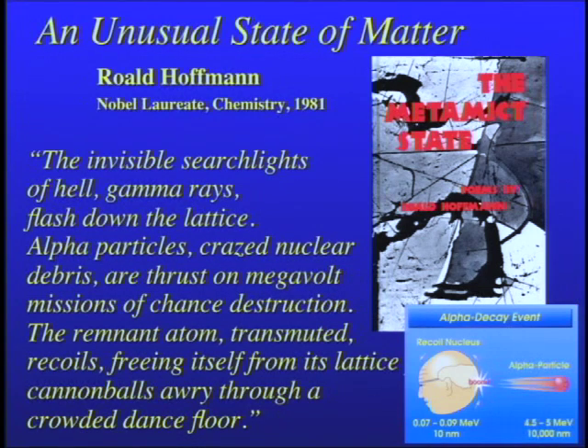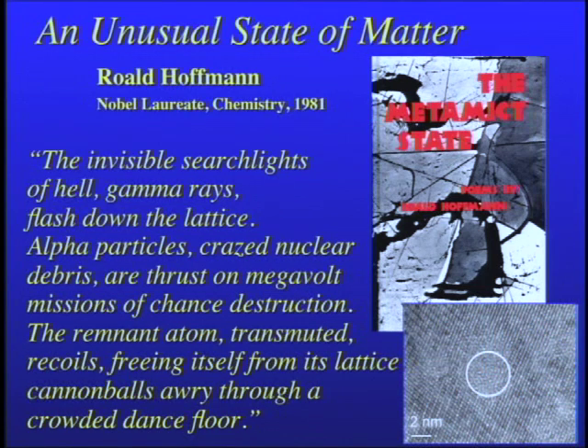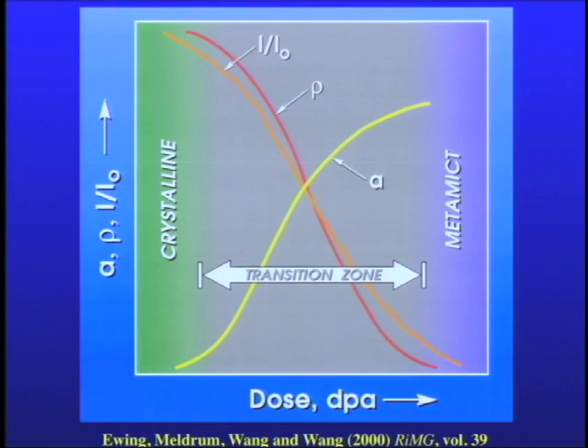And so you disorder the atoms, several thousand. Imagine them dancing, all properly arranged, but now this cannonball knocks them around. And with high-resolution electron microscopy, we can see this disordered recoil cascade at, say, 2 to 5 nanometers across. And that's what we're interested in, because as those cascades accumulate, they might also anneal, but as they accumulate, there are dramatic changes in the properties. The unit cell parameters expand because of the isolated defects. The density can decrease substantially, by 10 or 15%.